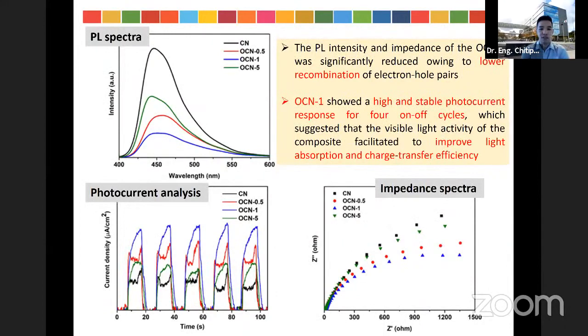And moreover, the excellent charge separation and transfer property of the OCN sample was proved by the photoluminescence analysis and the impedance. And the results show the photoluminescence and the impedance of the oxygen-doped sample were significantly reduced owing to the lower electron-hole recombination and the high electron transfer. Also, the oxygen-doped sample shows a high and stable photocurrent response, which suggests that the composite facilitates improved light absorption ability and charge generation under visible light irradiation.